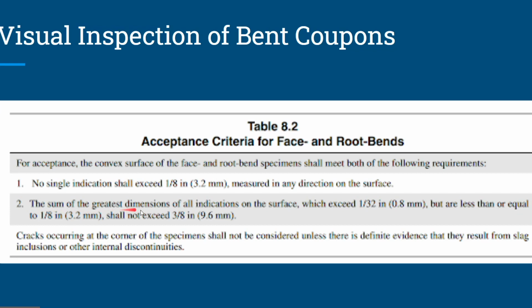The sum of the greatest dimensions of all indications on the surface which exceed a 32nd of an inch, but are less than or equal to 1/8 of an inch, shall not exceed 3/8. It's kind of wordy, but what they're saying is if it's less than a 32nd of an inch, we just completely ignore it. So it could be a crack, could be a slag inclusion, porosity, lack of fusion area, whatever it might be. If it's less than a 32nd of an inch, we don't count it.